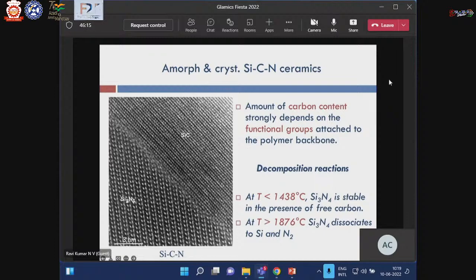This is a microstructure where you see a nanocomposite of silicon carbide and silicon nitride directly in crystalline contact, a pure grain boundary. Of course, this has been produced through the precursor route. And whether you have additional free carbon or not depends on the functional groups attached to the polymer backbone. But to what extent such a material is thermally stable depends on to what extent silicon nitride is stable. And as you see here, silicon nitride is stable in the presence of free carbon till a little less than around 1438 degrees Celsius. But beyond that temperature, silicon nitride in the presence of carbon will convert to silicon carbide in the presence of nitrogen gas.